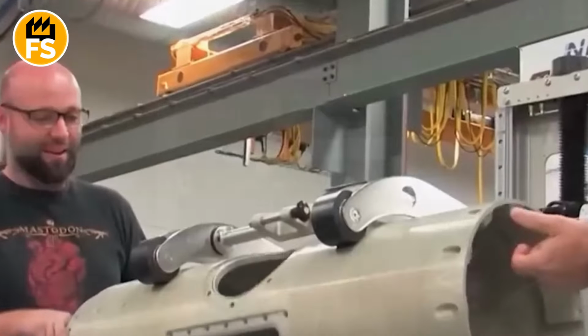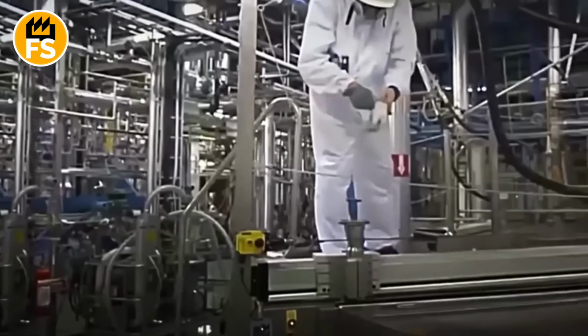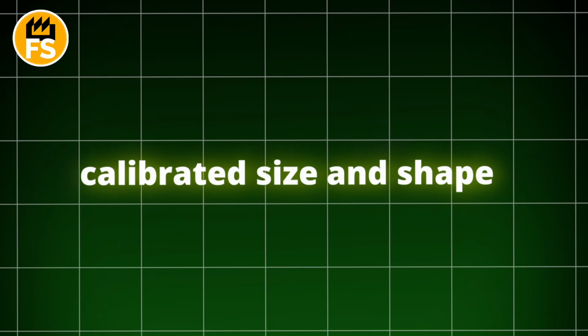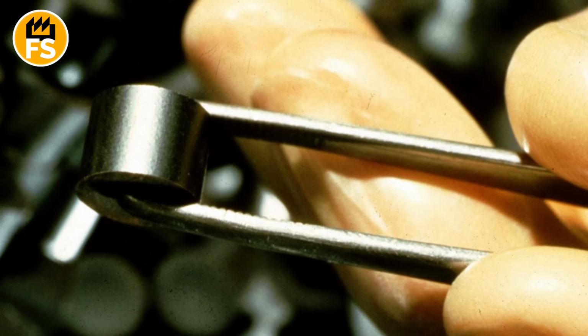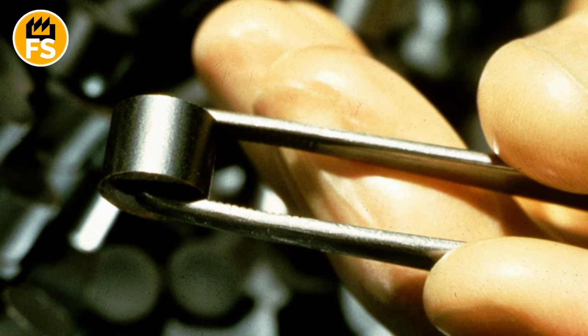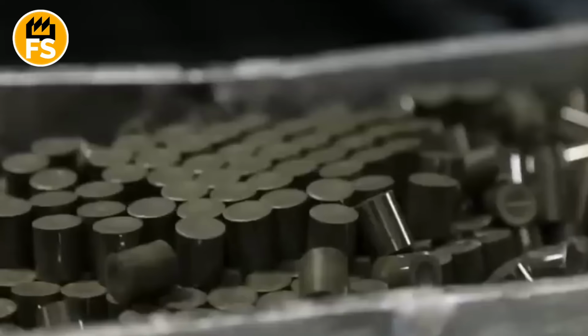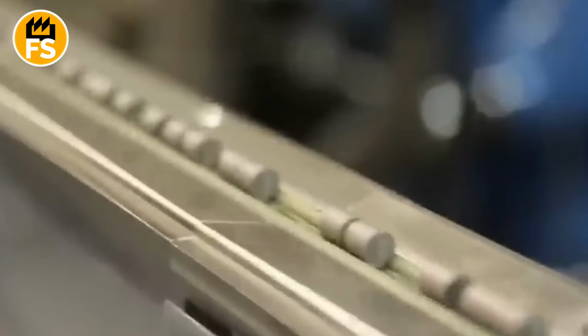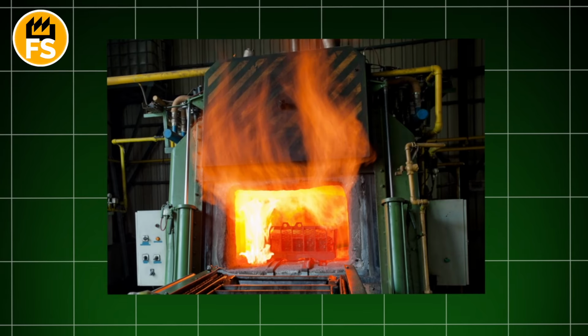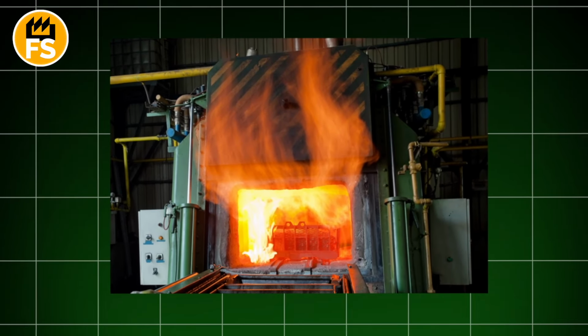With the help of chemical reactions, it is turned into a black powder of uranium dioxide. But this is not just any powder. Each of its particles has a perfectly calibrated size and shape. Now the most interesting part begins, the creation of fuel pellets. This black, heavy powder is sent to a press. Imagine a high-precision pharmaceutical press, only instead of medicine, it stamps radioactive pellets. It compresses the powder with incredible force, turning it into small, dense, perfectly cylindrical granules, or pellets. They are still brittle, like chalk. To give them strength, they are sent to a furnace. But this is not an ordinary furnace. This is a high-temperature furnace, filled with hydrogen to prevent oxidation.